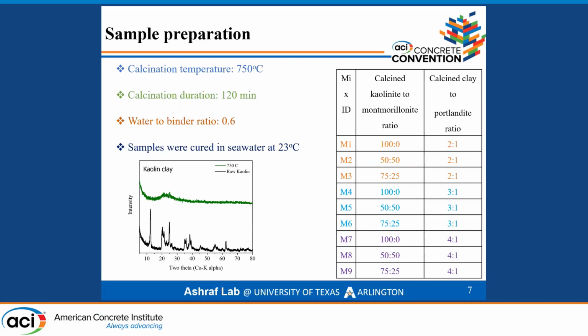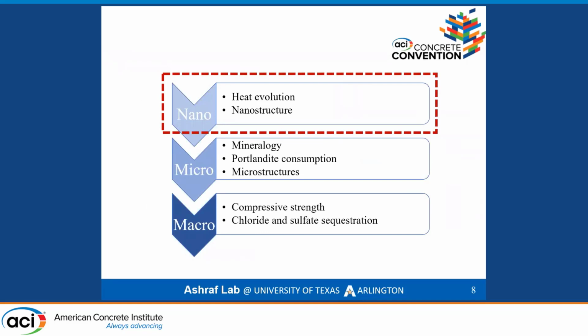We took two types of clay in three different ratios. First one is 100% kaolin, second one is 75% kaolin and 25% montmorillonite, and third one is 50% of both of the clays. We mixed this clay mixture with the Portlandite in three different ratios, 2:1, 3:1, and 4:1. Now let's talk about the nanostructural properties.